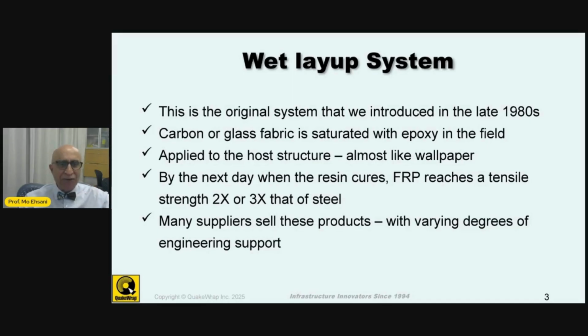glass fabric. And I don't know if any of you have seen this or not, but this is what I'm holding, a piece of carbon fabric, about 6 or 8 inches wide, but they come in different widths, and as you see, it's very flexible. So with the wet layup system, we saturate this fabric with epoxy in the field and apply it to the structure, almost like wallpaper. It goes on fairly easily, and by the next day, when this resin cures, you get a product which is 2 to 3 times stronger than steel in terms of its tensile strength.